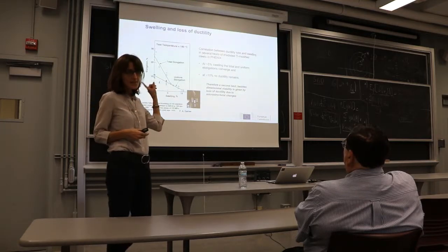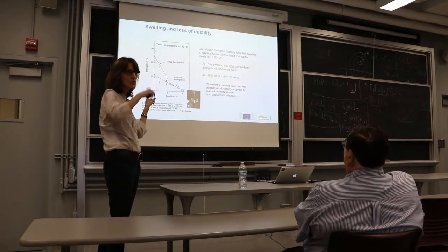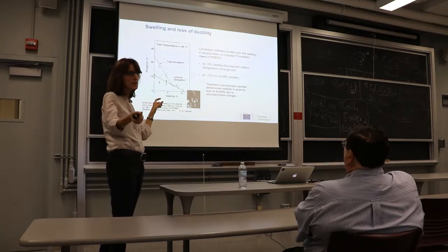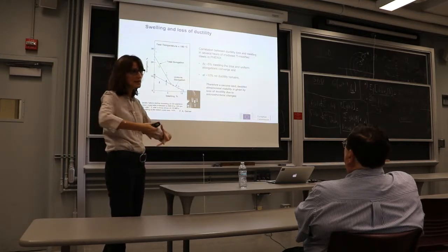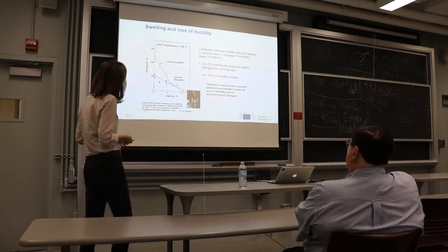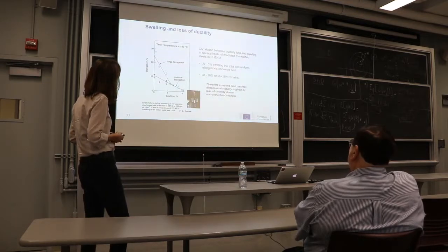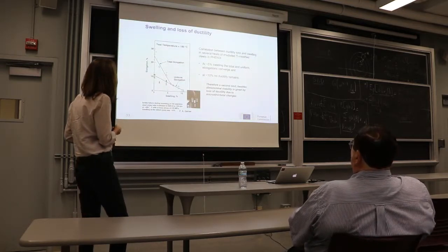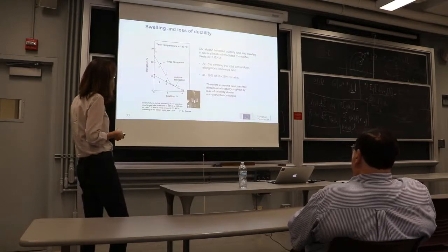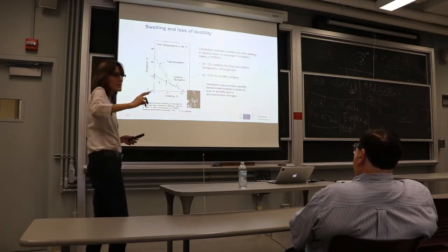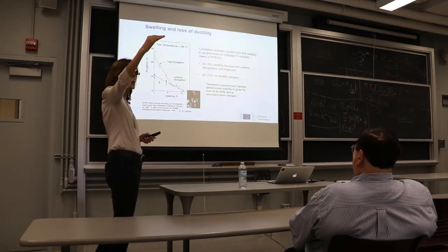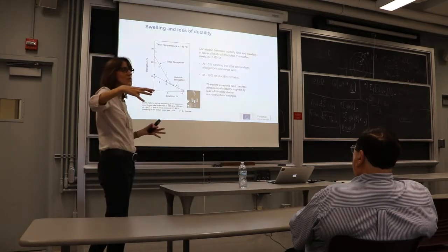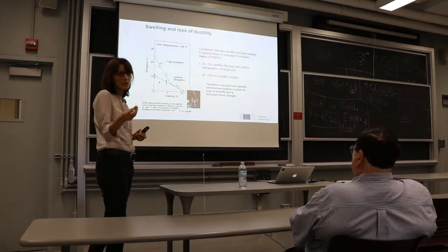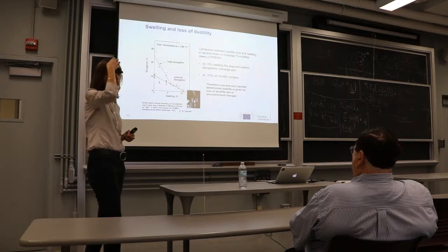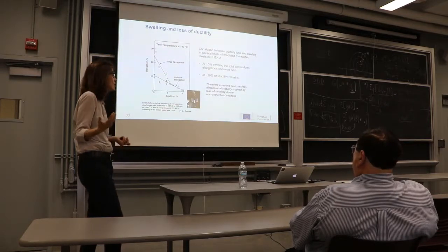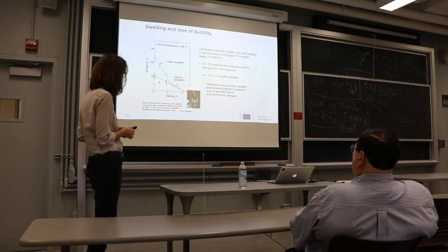And in this case, it's the nickel doing the problem, because the nickel, while irradiated, creates helium. Helium is trapped, and then it starts to increase in dimension. And the other point is that it has two problems. The second problem is, while it is increasing in dimension, so while it is swelling, it starts to be brittle. So it starts to behave in a way that is not wanted when the material is inside the reactor.